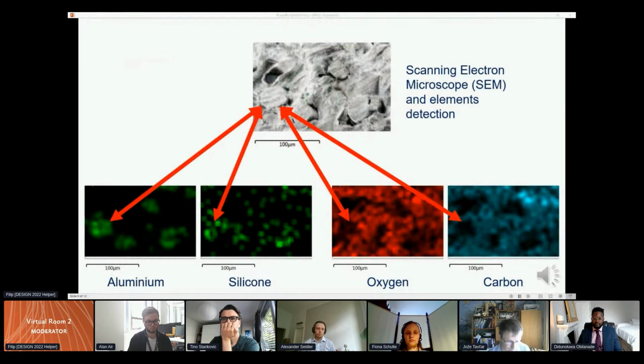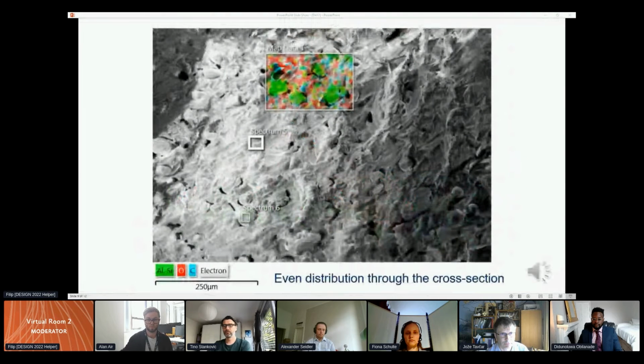The samples were analyzed with a scanning electron microscope. The image shows presence of elements. If we compare mapping, we can see aluminium and silicon are located in the black spots of carbon and oxygen. That means both groups of elements exclude each other. We have done elements mapping on different locations of samples, and they were evenly distributed.